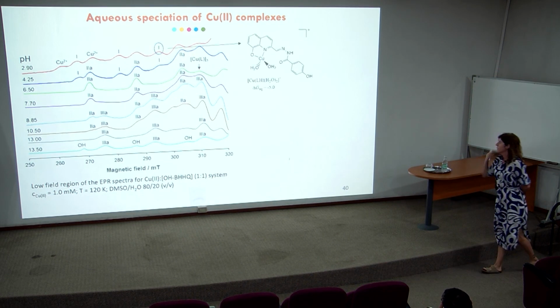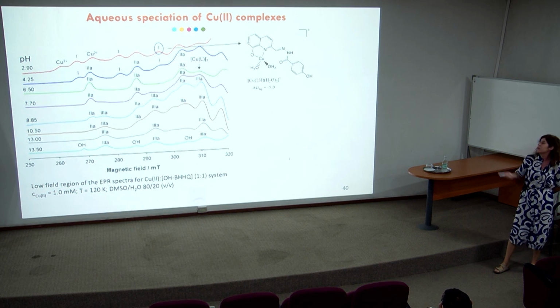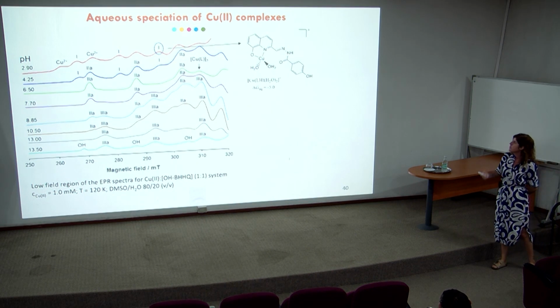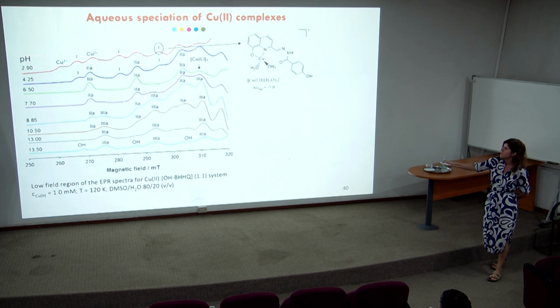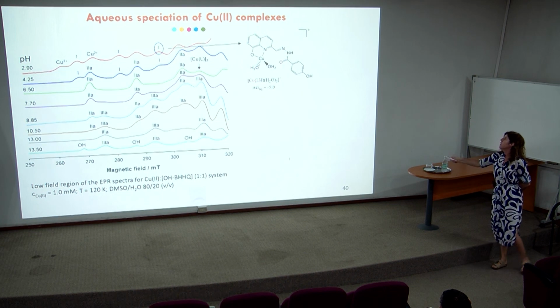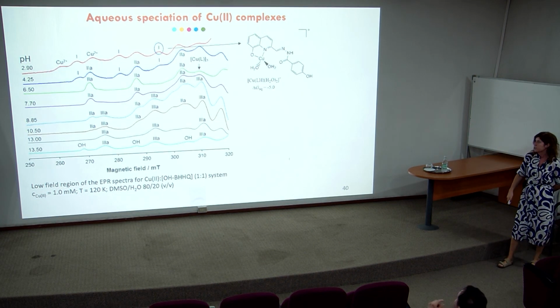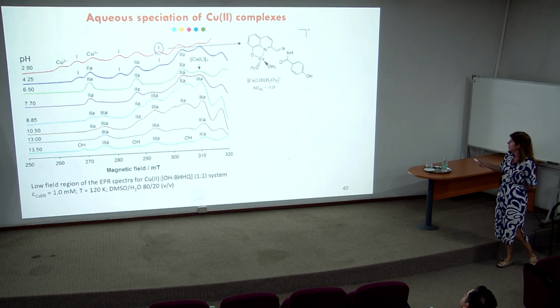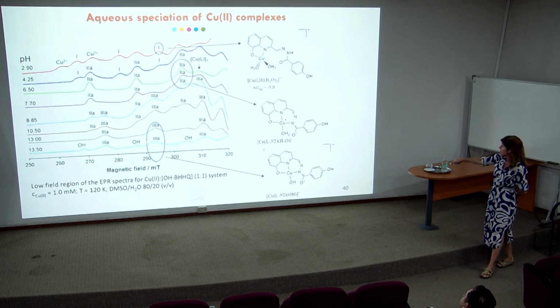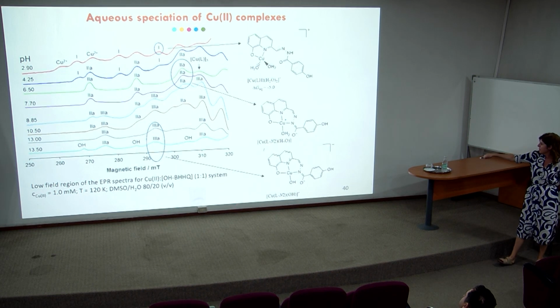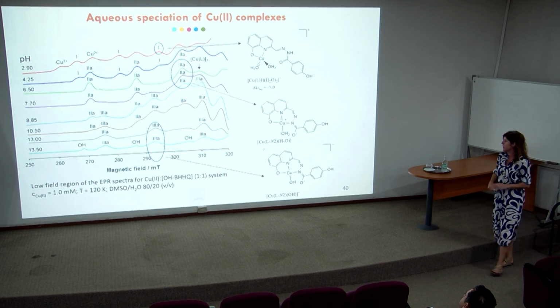We also use the DFT to propose different binding modes at different pH values. For instance, at pH 2.9, we have a copper coordinated to the 8-hydroxyquinoline, and upon the protonation of this group, different species are formed at different pH values.